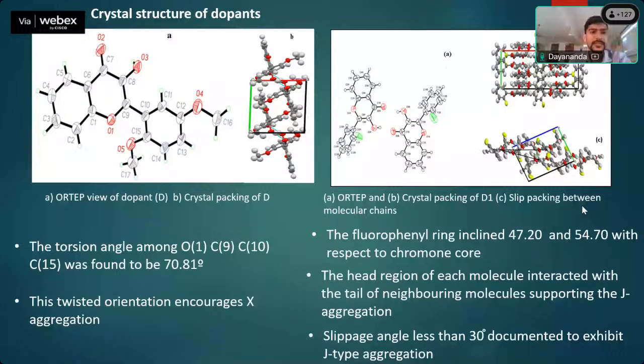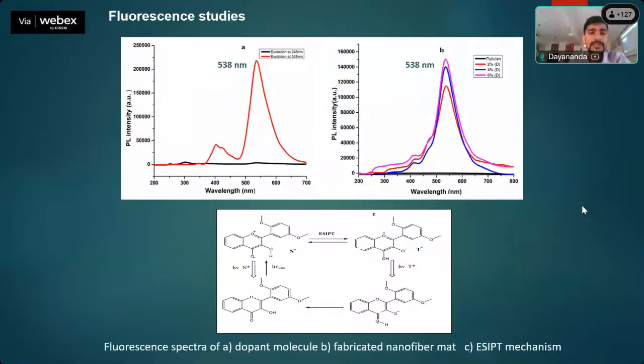From the fluorescence studies, it was found that the dopant was dual emissive, and the emissive profile of the nanofiber mat was similar to the dopant. There was no change, mainly due to the J aggregation of the molecule, since the compound was twisted in its crystal, it retained its original emission profile.